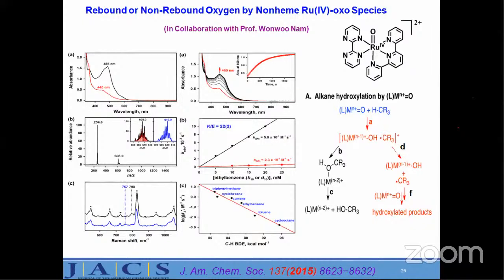In the non-rebound mechanism, this radical escapes from the cage. So this is a cage, and this radical escapes from the cage, right? And then it can be trapped by a substrate like bromotrichloromethane. So some substrate like that can be used, and then the radical can be trapped. It escapes and finally gives the hydroxylated product. And of course the metal plus 4 oxidation state goes to metal plus 3, and that is the reason the yields are low. So based on this background, we thought, let us see.